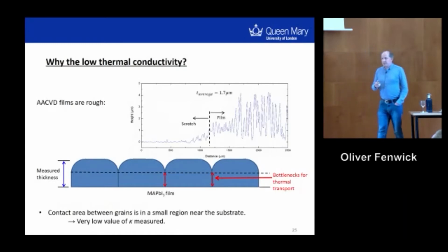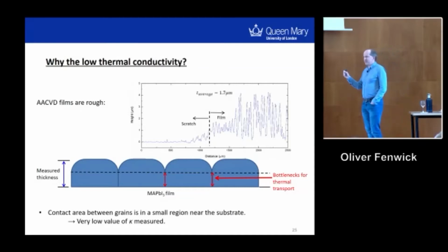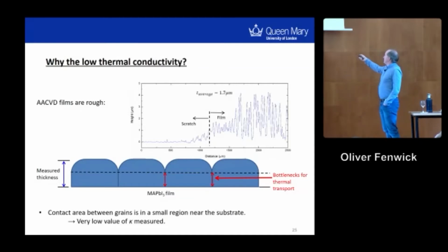So why the low thermal conductivity? This has a relatively straightforward explanation, but I think it's an important one for you to be aware of. And this is that these AACVD films are rough. I should mention, by the way, that the people working on this have now improved the methods and they can get quite smooth films. They can do it very well now, but at this time, the films were very rough. What does this mean for measuring the in-plane thermal conductivity? Well, we're going to measure a certain thickness of the film, but actually the heat transport is going to have to go through various constrictions in the film. Every micron or so, there's a dip here. And that is really restricting the thermal transport, and they're really quite severe.